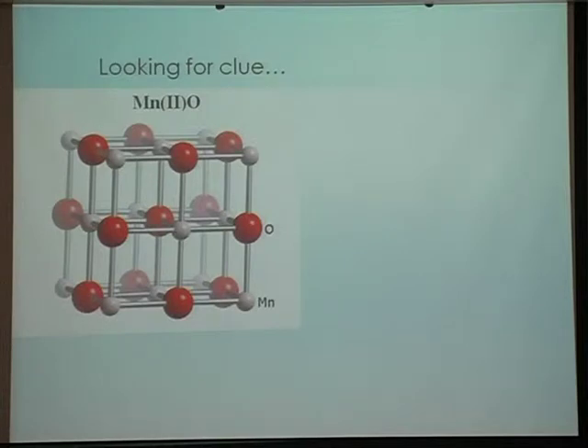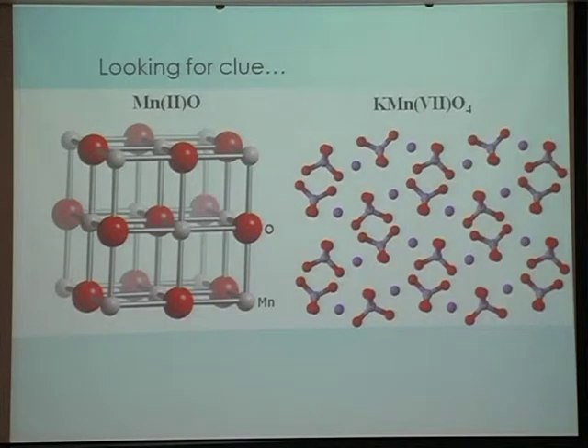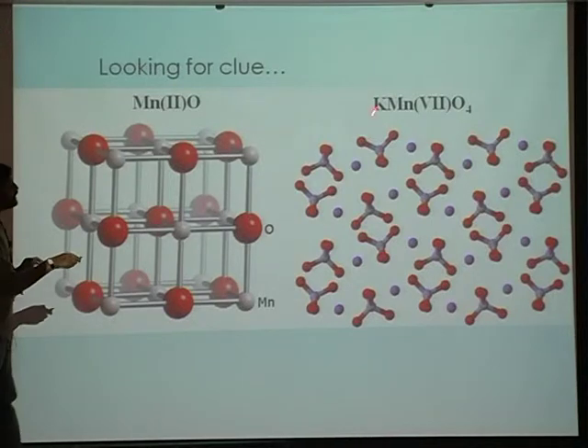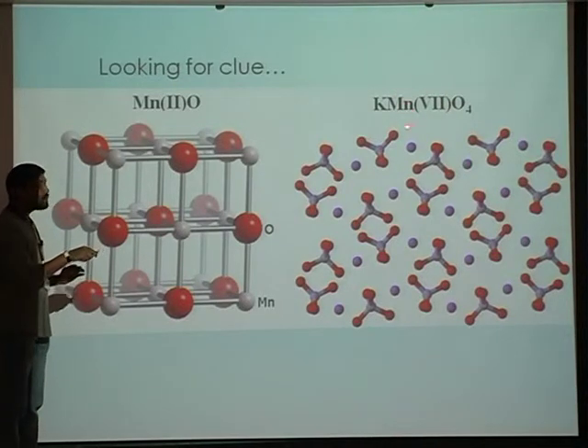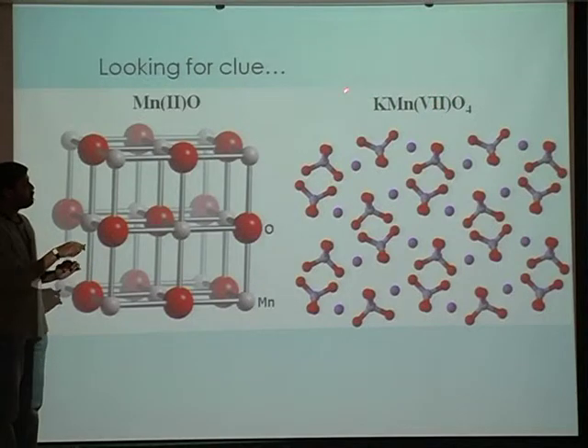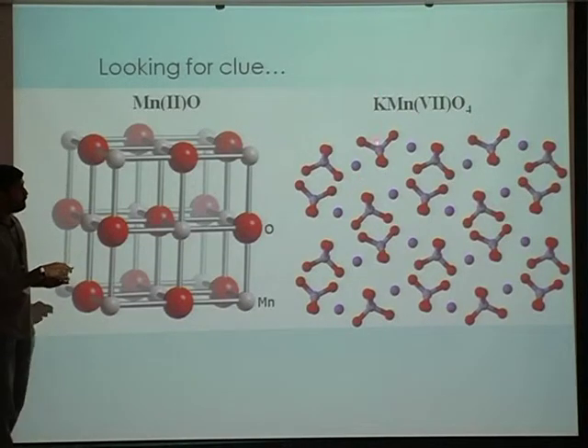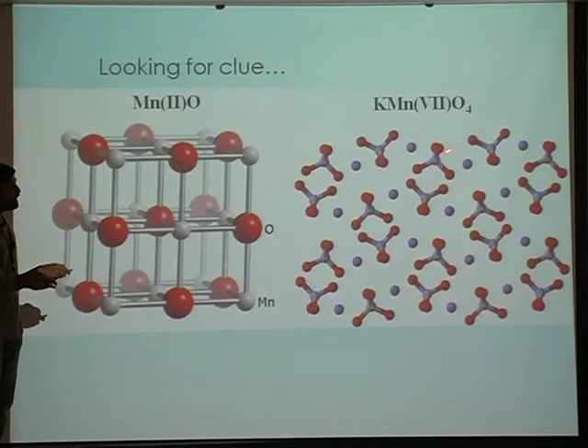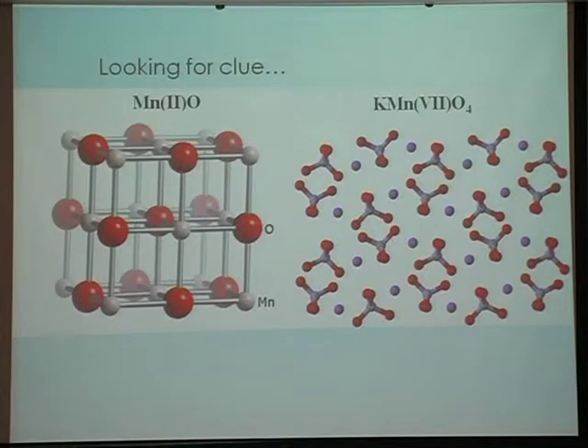Compared to that, I will show you another structure, which is the structure of potassium permanganate. What's that? Here the manganese is in 7+ oxidation state. Potassium is completely ionic. It just gives out its electron, sits here, does nothing else, and you are left with MnO4 tetrahedra, which are these. And this manganese is 7+. The point is, the manganese oxygen bond lengths are found out to be this.